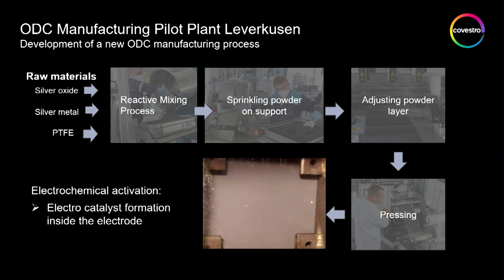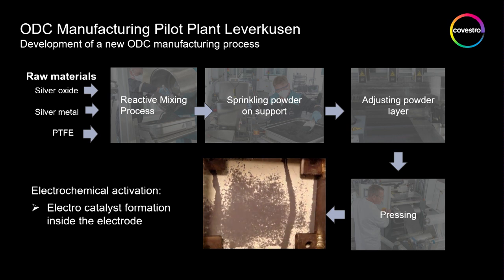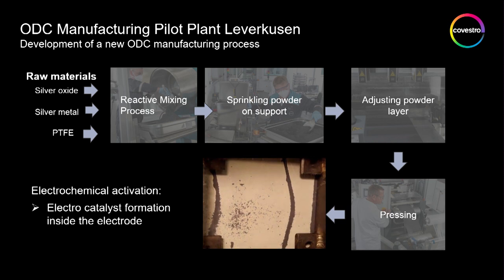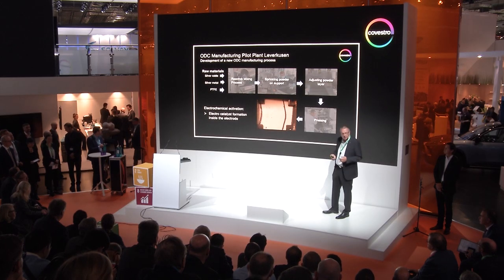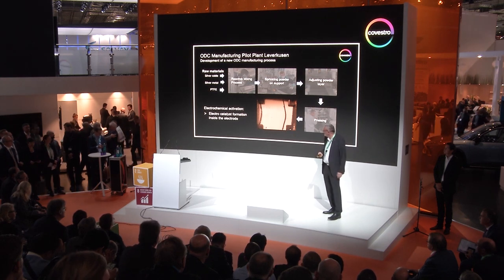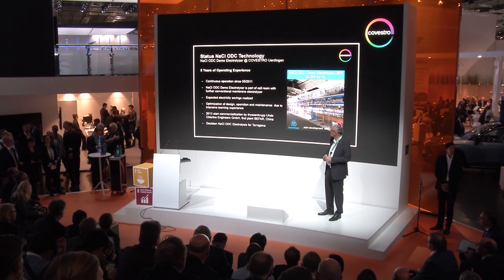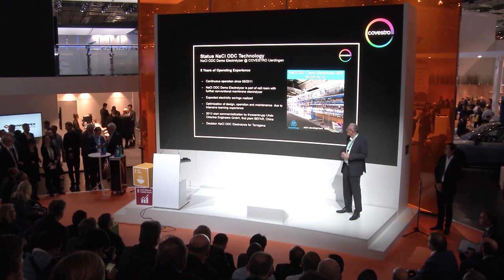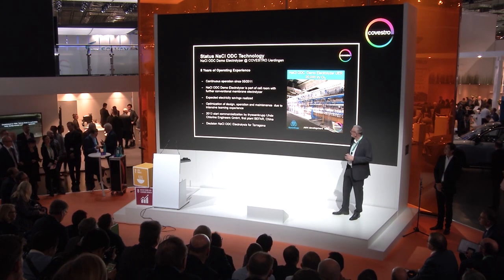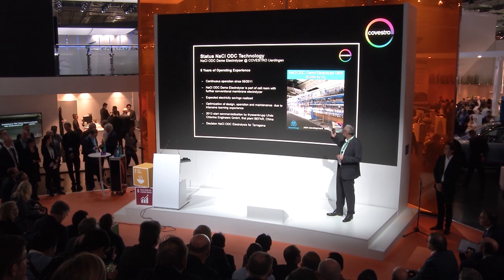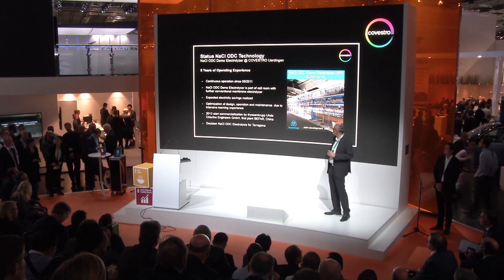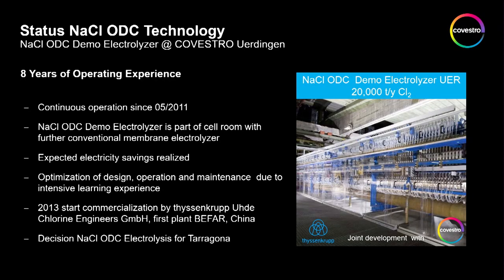During the first startup, you can see the precursor catalyst has a dark brown color. And during the first electricity put on this electrode, the highly active electrocatalyst is formed. You can see it has changed from the brown color to white. And once this catalyst has changed, the oxygen depolarized cathode is ready, and we have a highly active electrocatalyst working inside the electrode. So after a lot of work done in the lab and the pilot, we decided in 2011 to build a demo electrolyzer. And you can see here this electrolyzer at the site of Krefeld-Uerdingen.